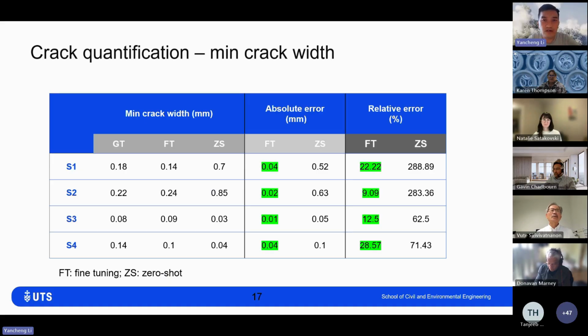We try to find the minimum crack width, because along a long crack there are some points which have a narrow crack. That's why maybe it's 0.1 or less than 0.1. We have 3 columns: ground truth, the real number you should identify, and fine-tuning and zero shot. You can see zero shot is quite exaggerating the crack width. From 0.18 it recognizes 0.7 millimeter, and somehow underestimates the crack width from 0.08 to 0.03.